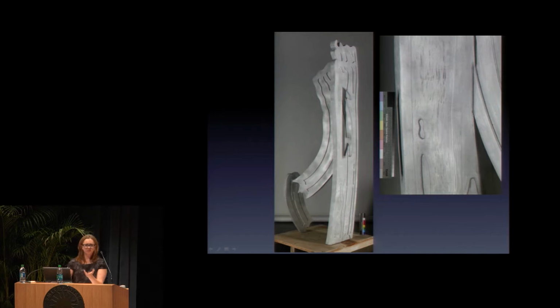In retrospect, and this is something that someone brought up in the past, there's an issue of redeposition, and I found that working in that environment, at that pressure, lots of paint stripper, lots of paint, it kind of went everywhere. And so I do feel like there was a bit of redeposition on the surface. After the company cleaned, basically scrubbed the tent in order to dispose of the waste, and the tent was brought away, I felt like it had a little bit of a film on it. And that made me a bit uncomfortable prior to repainting.